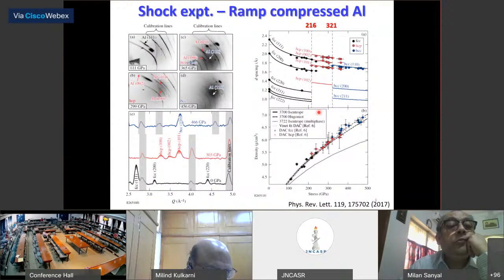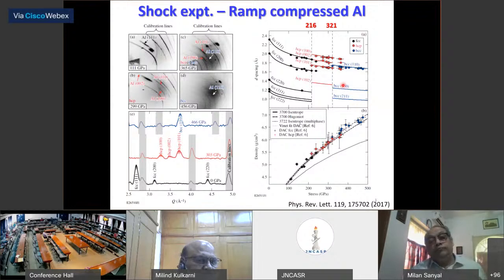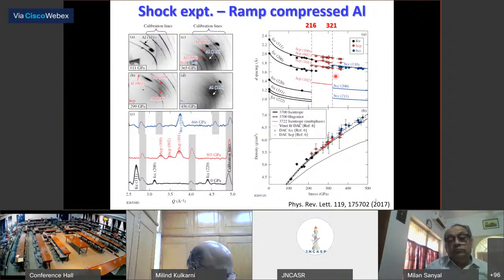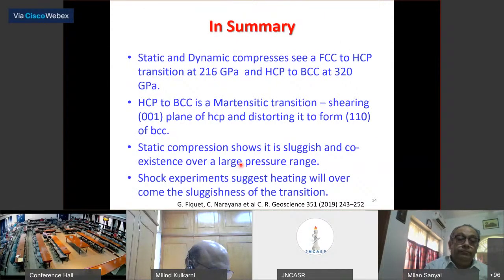We could show that. And along with the time when we were working, a shock experiment was also done. They could see very, very weak signals, but they could actually see BCC as the phase about to form. So this is what we had actually demonstrated using the synchrotron.